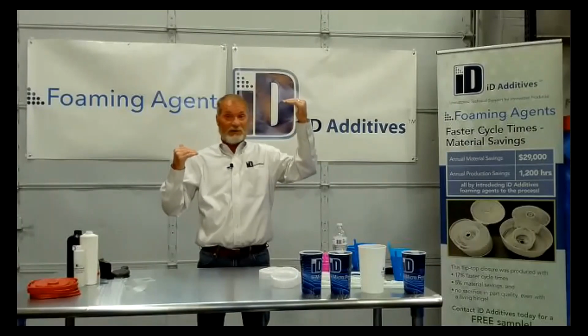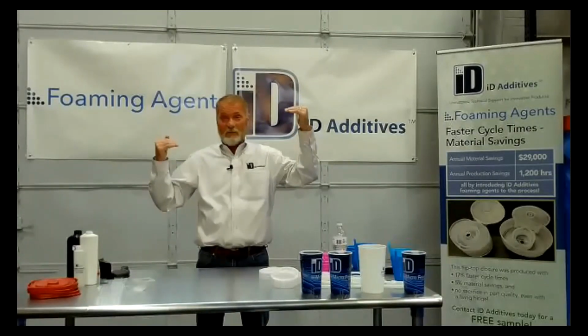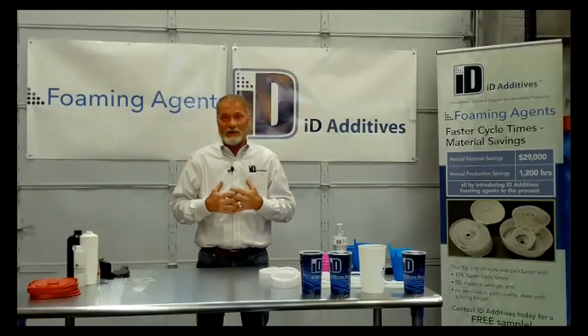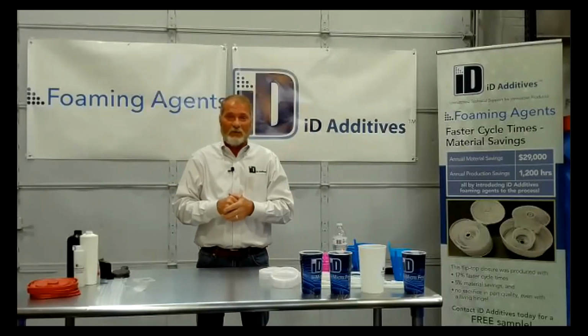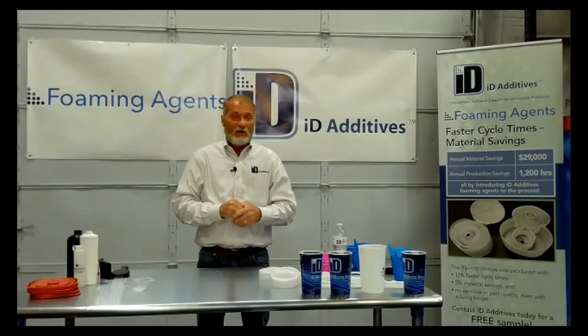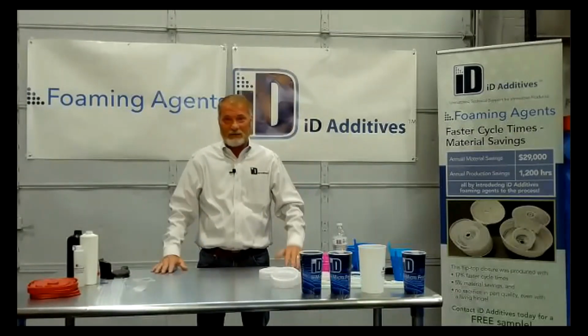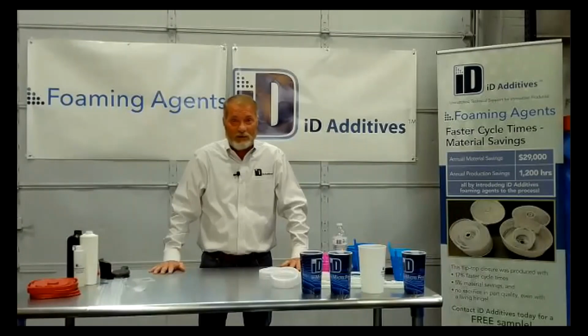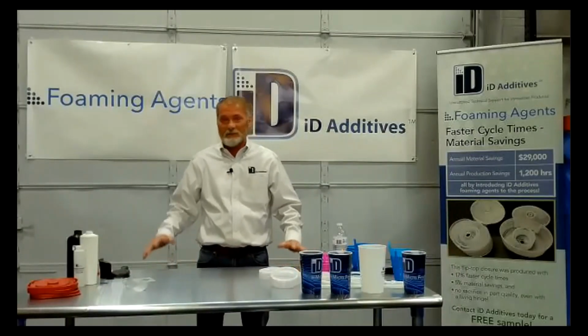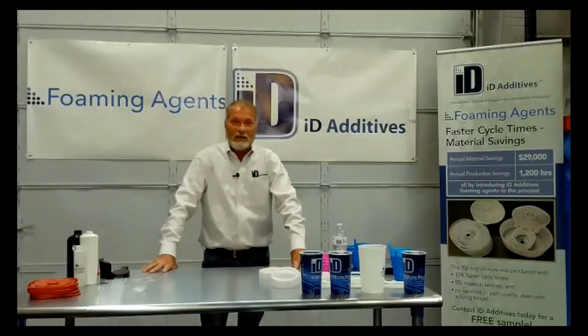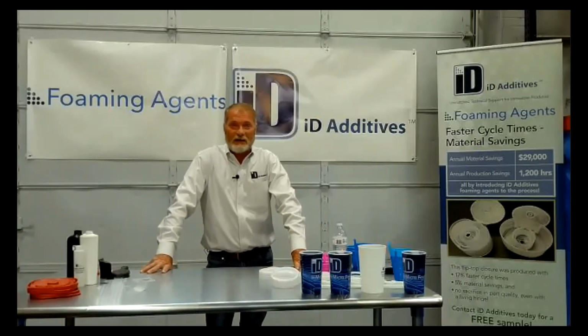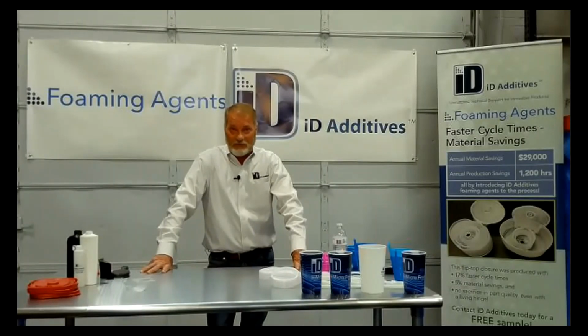But if you got too much nitrogen, you're just throwing away the foam. And I've always recommended in structural foam multi-nozzle a minimum of 0.5%. And everywhere I've gone, and maybe there's somebody out there that can show me otherwise, but everybody seems to think the 0.3 is the way to go. Well, for me, if you're at 1200 PSI or 1300 PSI or even higher and running 0.3%, you might as well throw that money out the door, because that 0.3 to me isn't doing anything for you.